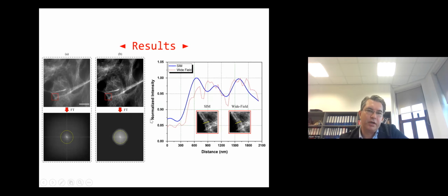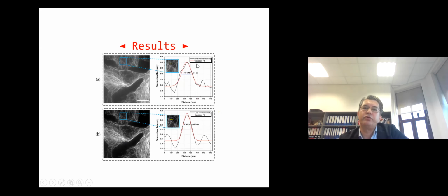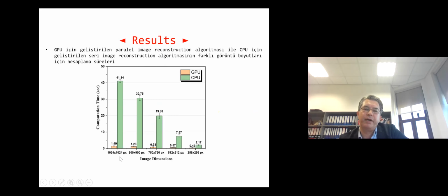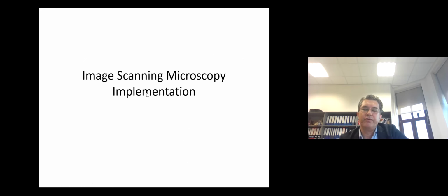Our implementation, first of all, gave better resolution as opposed to wide field illumination. For wide field, here you see 254 nanometers. For the SIM approach, we see 187 nanometers. So we improve the resolution, and we also speed up the whole process. Depending on the image dimensions, we speed up this post-processing by a large factor, more than a factor of 10, due to this GPU implementation. We also worked on a dot scanning approach in addition to stripe scanning. In the dot scanning approach, you have a grid of dots illuminating the sample, and you move this grid around to cover the whole sample. This approach is also called image scanning microscopy.